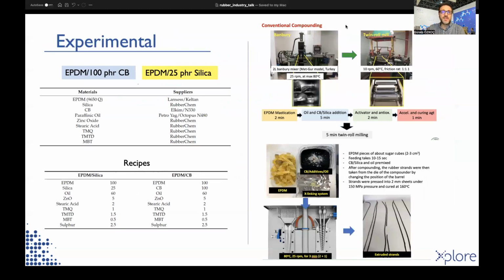For this purpose, we designed 2 recipes based on EPDM silica and EPDM carbon black. Here one should note that the mixing of carbon black into EPDM is much more favorable than those of silica due to its chemical compatibility, whereas dispersing silica in EPDM is challenging since the polarity of silica is different than EPDM. We have followed a sequential mixing route for the conventional mixing part in a 400 cc Banbury mixer.